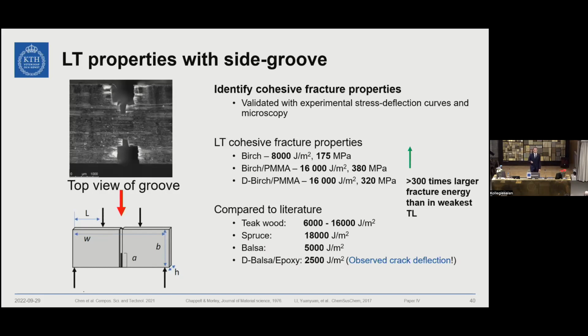Compared to literature that have done some similar types of tests, and not the same geometry, of course, they get roughly the same numbers as we are. So we are in the right region. One study that has studied densified balsa/epoxy composites estimated a much lower fracture energy, but they also observed this crack deflection.